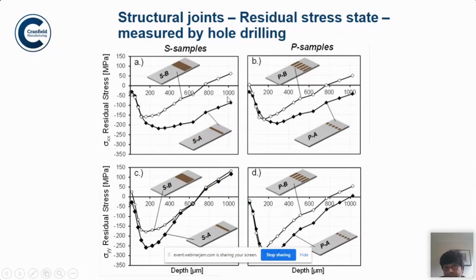So these are some examples. There are different types of peening that we studied. We call this stripe and we call this batch. As you can see, the peening process creates a good amount of residual stress. This is the compressive stress, which is balanced by tensile far away in the plate. This plate is 2.3 millimeter thick, and the crack will propagate through the thickness. So the main target is to prevent the crack propagation through the thickness.